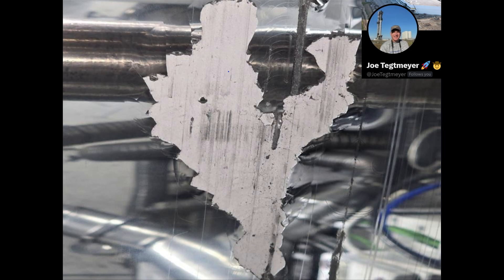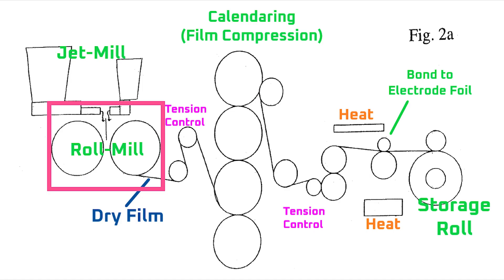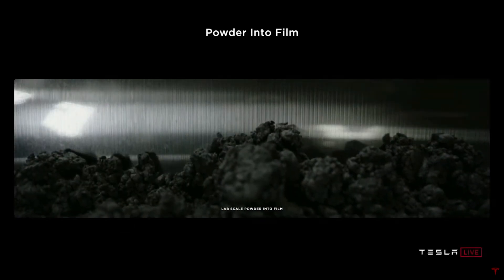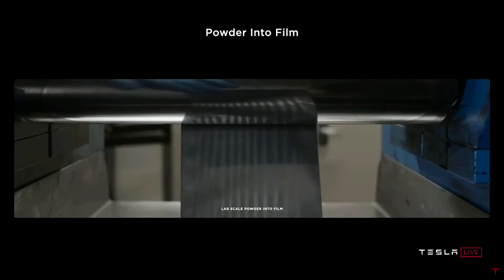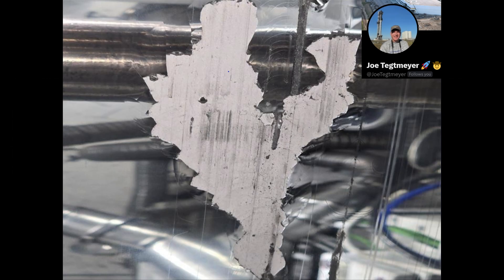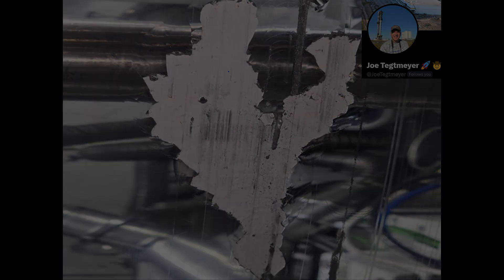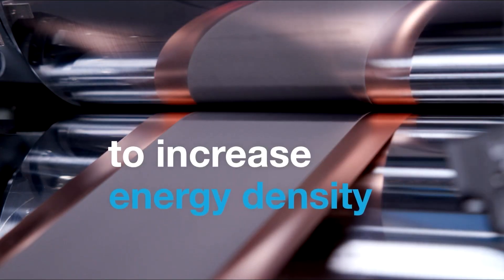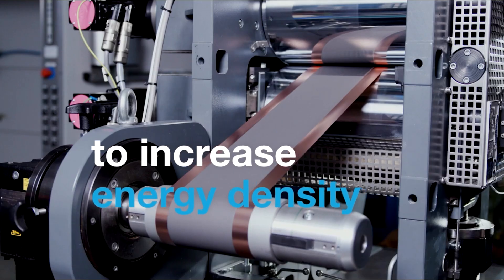For the image of the damaged cathode roller, I suspect that the roller we're looking at here is the roller for the roll mill. That's because the roll mill would have to rapidly squeeze and evenly distribute large volumes of material to form the freestanding film, which means extreme stress that could dent the rollers or cause the delamination seen here. That's as opposed to calendaring, where the material is already fairly uniform, so the compression stresses wouldn't be as great.